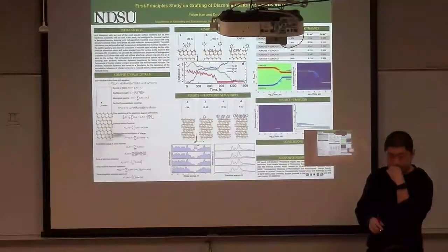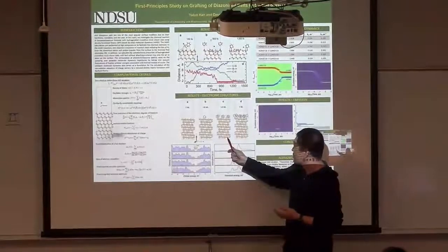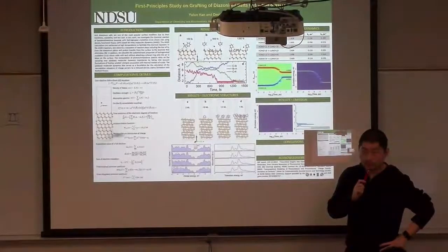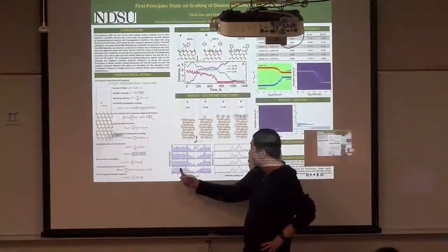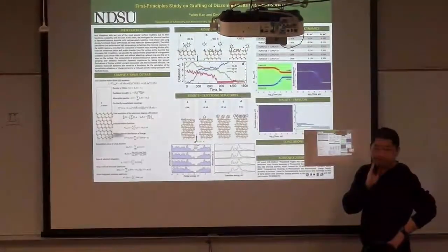Sorry, you said you didn't see much change in the density of states before or after the addition of those ligands, or those groups, up until this point. What is a half ML? Monolayer. Okay, so why did you not see a difference up until that point? Did you hypothesize what it looked like? If you see the p DOS, we can see the carbon orbital is very deep. It's deep inside, so you have to have more crowding on the surface to have a change. Okay.